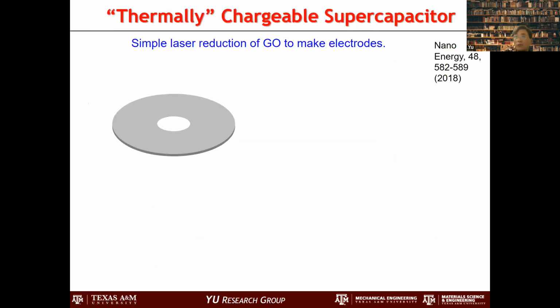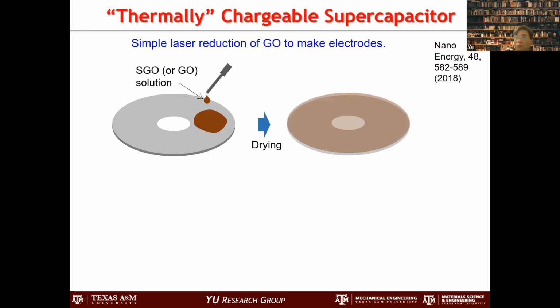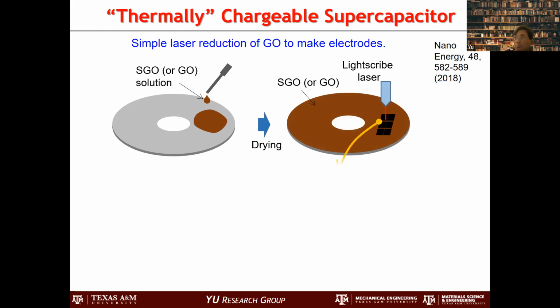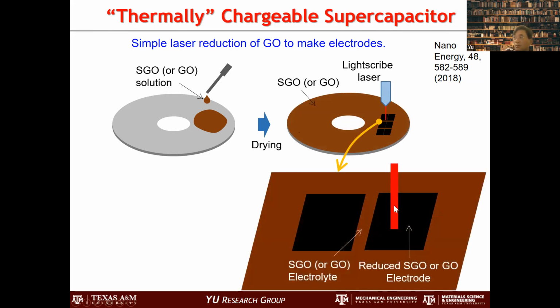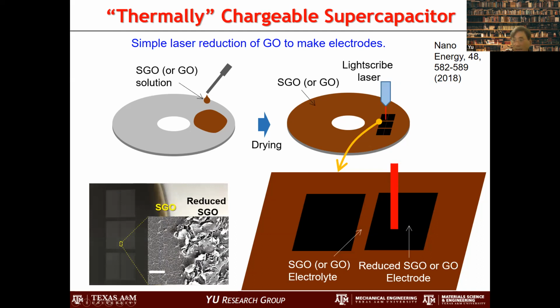So in this case, what we use to make that is graphene oxide, and we do a drop casting of this solution, because graphene oxide is soluble and dispersible in water pretty easily. Then we drop cast, we dry it, and we use a laser to scribe it, and here it becomes reduced, and this becomes the electrode, because graphene oxide is electronically insulating, and when we shine the laser on top, it becomes reduced graphene oxide, and electronically conducting. So this is electrode, this is electrode, and in the actual SEM image, this reduced part is electronically conducting, but this is not. This is an ion conductor, but electronically it's not conducting.